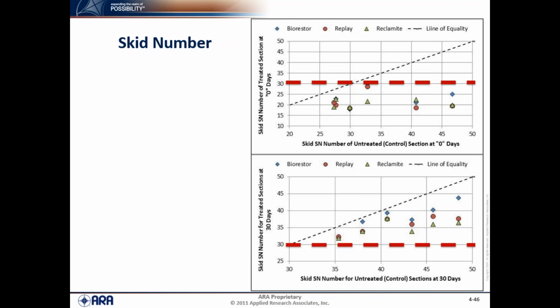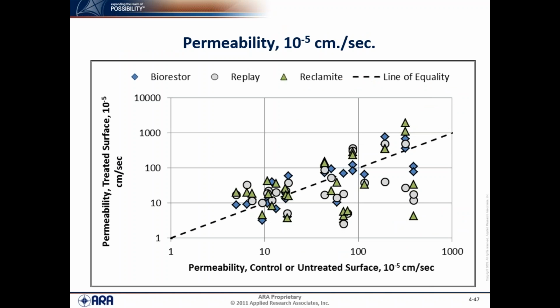If you look now at the lower graph, there's also our red dashed line at a skid number of 30. The x-axis is the skid number for the untreated control sections at 30 days, and the y-axis is the skid number for the treated sections at 30 days. Now the important part here is that they're all above a skid number of 30 at 30 days. But you can still see that all of the treated sections consistently still had skid numbers lower than the control section. I'll come back to this when I talk about some of our findings a little bit later.